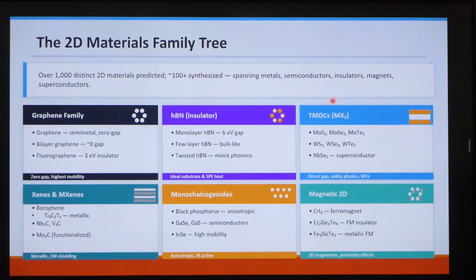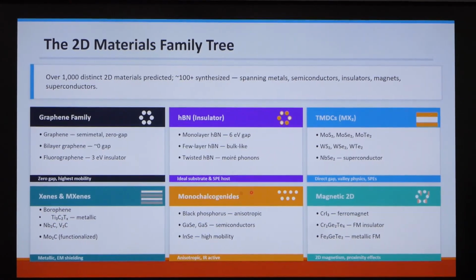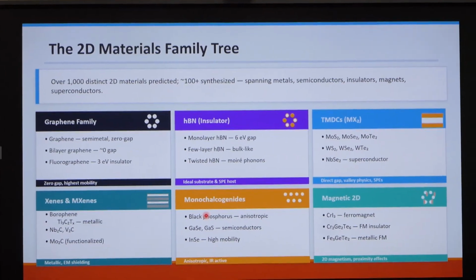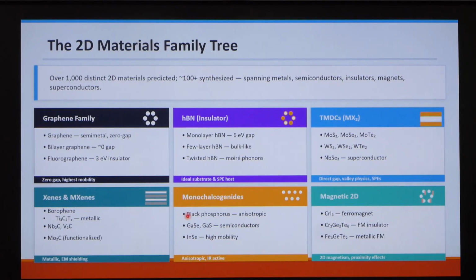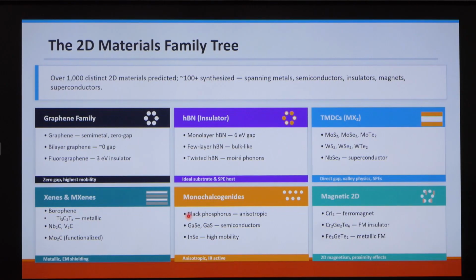Then we have the other things, as I said, about the Xenes and the MXenes, that is, the metallic MXenes, and then monochalcogenides. These are transition metal plus chalcogenides, meaning sulfur, selenium, tellurium. In your periodic table, they are called the chalcogenide group VI. Here it is monochalcogenides, meaning you don't need any transition metal, rather directly phosphorus, P, right? They are black phosphorus, only phosphorus, nothing else. So we get black phosphorus or gallium selenide, gallium sulfide.